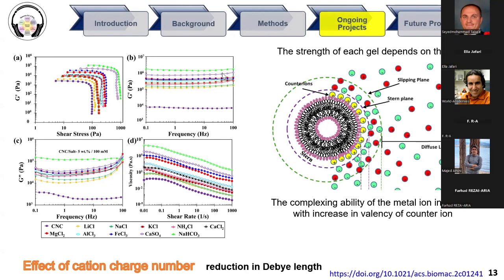First, as I told you, the first parameter is the cation charge number. As you can see in this slide, take the green line as an example. The sample includes sodium bicarbonate, NaHCO3, salt, and it has the highest viscoelastic properties and viscosity. So we need to find out why. The first reason is cation charge number. By increasing cation charge number, I mean moving from monovalent salts to divalent and trivalent salts, we can increase the viscoelastic properties. But what is the reason for that?